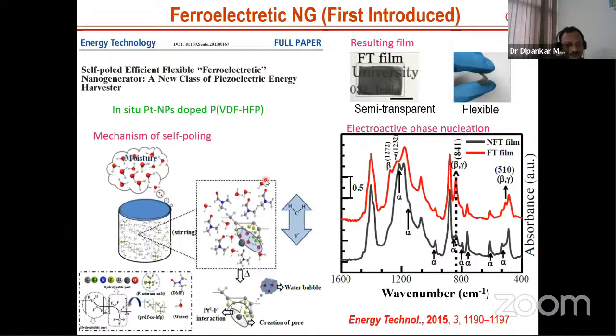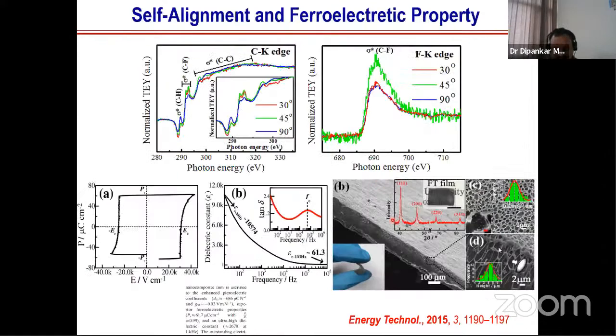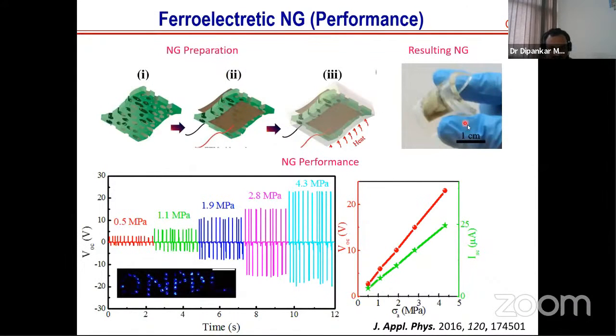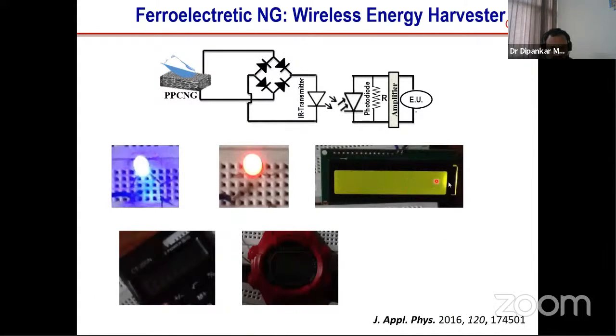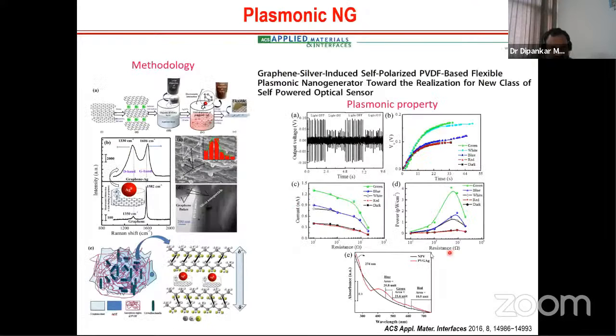This is another approach where we made porous materials, and this beta phase is there. You see how porous it is. You see the nanoparticles are there, and we made the porous structure. This is the cross-sectional image, and this is some spectroscopy by which we can say we have very oriented dipoles here, and you see we have reached a very high dielectric constant. And then this is the device structure. If we give pressure, we can light up the LEDs, and we can even light up an LCD screen and a wristwatch and so on.